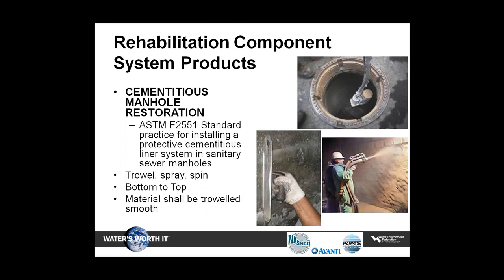For cementitious manhole restoration, ASTM F2551 shall be followed. Product shall be applied using equipment specifically designed for troweling, low-pressure spray, or spin casting. All cementitious liners shall be troweled to densify and smooth out the surfaces.